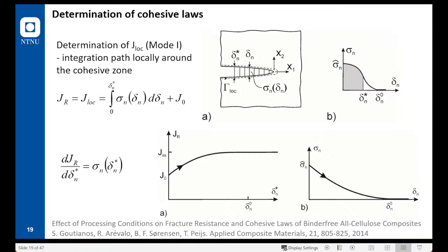I will not go into details in this slide, but I will only mention that we use the J integral. We calculate the J integral around the fracture process zone. These are the bridging fibers, the process at the crack tip. If I plot the J integral with respect to the opening of the fracture process zone, I will typically get such a behavior. And then if I take the derivative, as you can see here, I can calculate the cohesive law. For simplicity, I'll give only the mode 1 cohesive law. That means normal opening on the x-axis and normal traction on the y-axis.